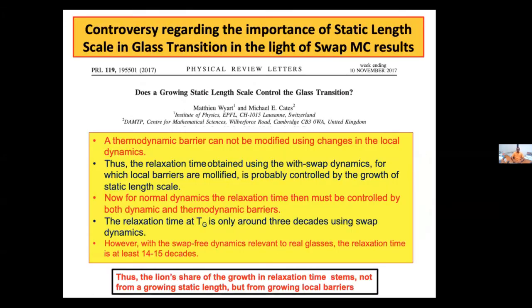Along with this, there is a controversy which came in, which is the work of Matthew and Mike Cates. They said that swap Monte Carlo speeds up the dynamics by a very, very large factor, and even at Tg the swap relaxation time is of the order of maybe 10 to the 3 to 10 to the 4. So probably there is no growing static length scale that controls the glass transition, and the argument was that if a local move can remove all your barriers, then those barriers are probably not thermodynamic in origin. If they are not thermodynamic barriers, then RFOT-like theory and the associated length scales are probably not the main player in understanding the physics of glass transitions.